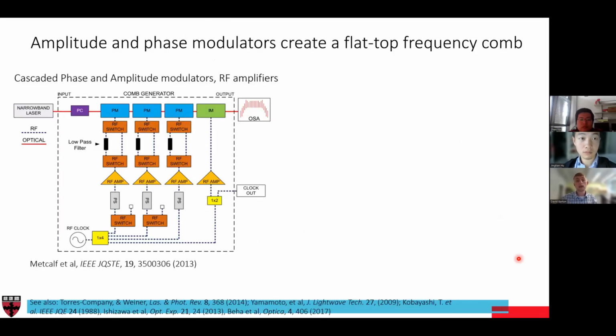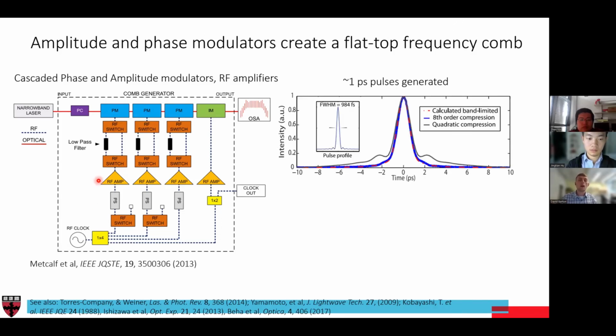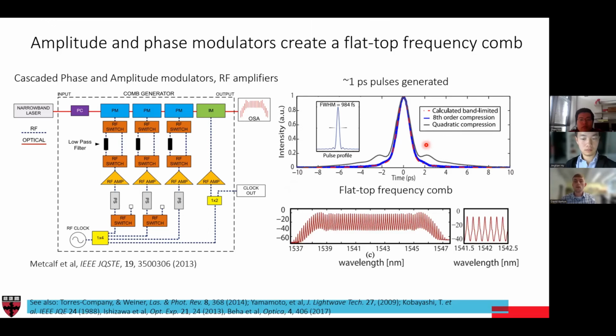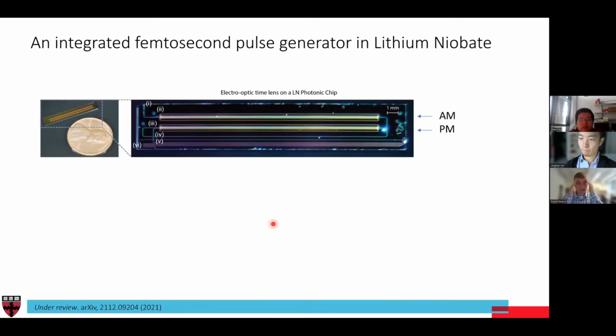This has been done in tabletop by using a couple of lithium niobate amplitude modulators, phase modulators, a variety of microwave equipment. Actually, a lot of controls go into these sorts of measurements. And what you end up getting, for this specific example, is about picosecond pulses. If you look at their frequency components, you see a variety of different frequency components that span about 10 nanometers here. These are very flat frequency comb lines that you can, for example, use in communications. For example, you can modulate on individual frequency components and send information along each of these different comb lines.